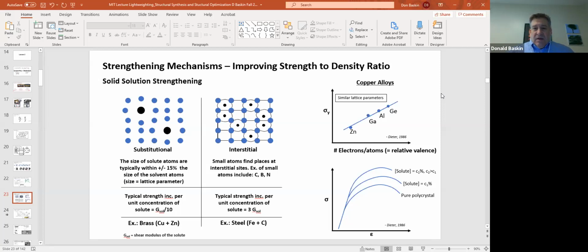You can get substitutional when the radius of the substitutional solute atom is within about plus or minus 15% of that of the primary base material atoms. The typical increase in strength is about the shear modulus of the solute divided by 10. That's what you get from adding these substitutional alloys. An example of a substitutional alloy is brass.